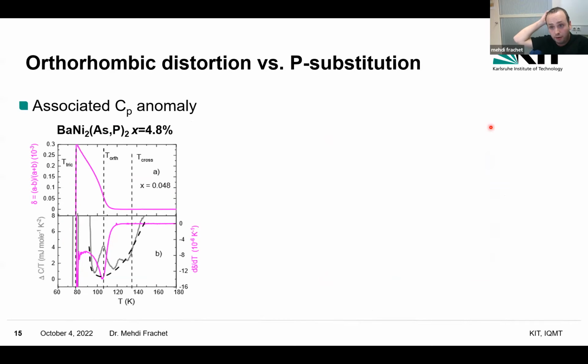Now, Christoph Meingast has also studied the evolution of this orthorhombic distortion with phosphorus substitution, and I'm showing you an example at 5%. You see the orthorhombic distortion as a function of temperature. You can see that the transition now is close to 100 Kelvin, so it's already quite substantially shifted to lower temperature. And what I want you to look at is actually the amplitude of the orthorhombic distortion. That's super small. That's like 1 order of magnitude smaller than in barium iron 2 arsenic 2. Okay. What you can see on the lower panel is actually also a specific heat, a tiny specific heat anomaly, which is associated to this second order transition.